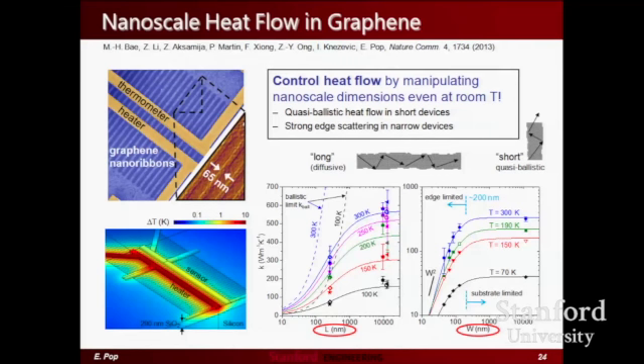And so, again, to make a long story short, we measured this, ranging from room temperature all the way to lower temperatures as well, but not too low. I mean, from about 70 to 100 Kelvin, all the way up to room temperature, 300 Kelvin. And to our surprise, not only are we approaching these so-called ballistic limits at room temperature, so energy, heat flow, is actually approaching the ballistic limits at room temperature in this material in samples that are small enough. Not only did we find that, but we also found out that we can manipulate the way that heat flows in these nanoscale devices by changing the dimensions of the device, right?